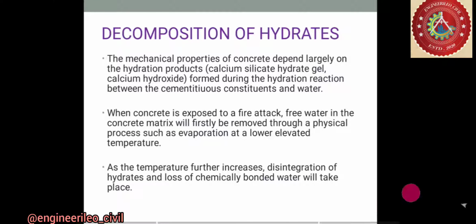Low permeability and dense microstructure of high strength concrete are probably the causes for creating high pore pressure, which has been considered as a key factor for explosive spalling of the concrete. In concrete with compressive strength of less than 60 megapascal, no spalling would take place.